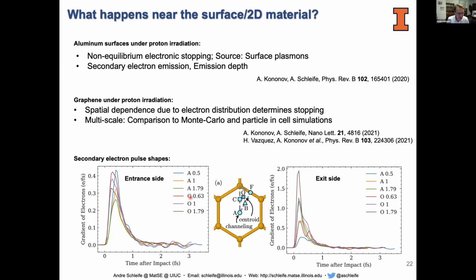So these letters here indicate different trajectories that we shot the proton through the graphene. The numbers behind them are velocities. You can see it's preliminary data because it's not polished yet, but the numbers are velocities of the proton in atomic units of velocity. And you can see that, for instance, let's say we look at the A trajectory on the left-hand side. In this case, the pulse becomes stronger as we go down in velocity, and this trend is exactly reversed on the exit side. So we're currently trying to understand those kind of trends.